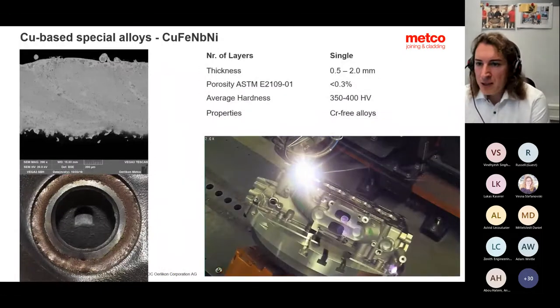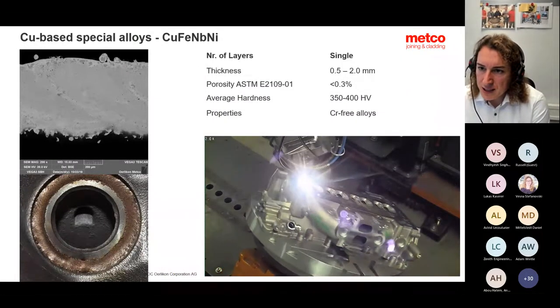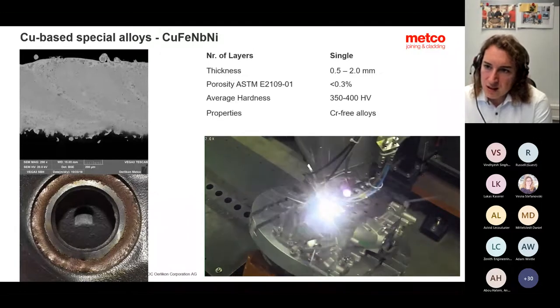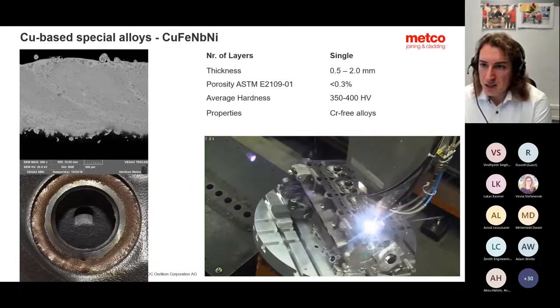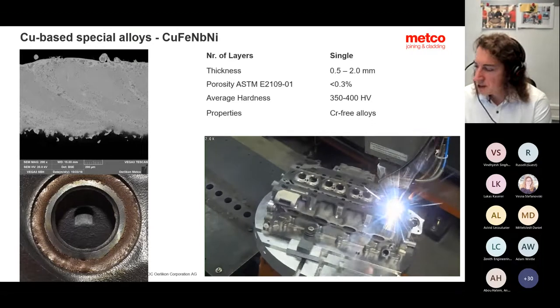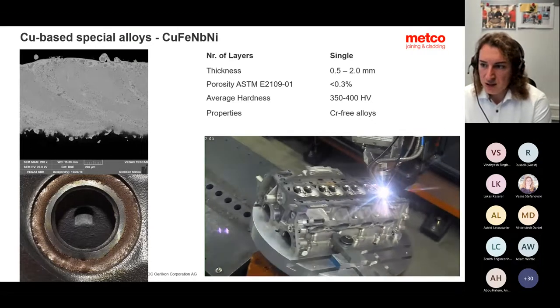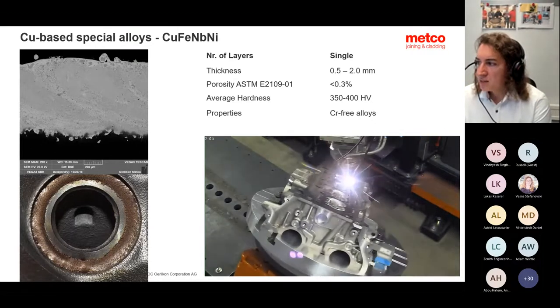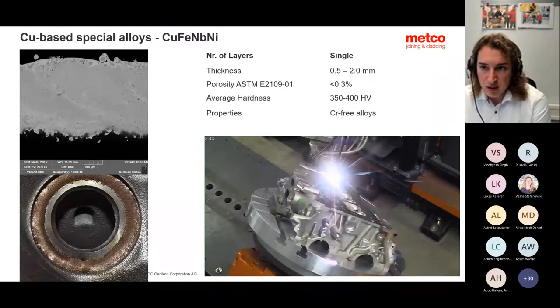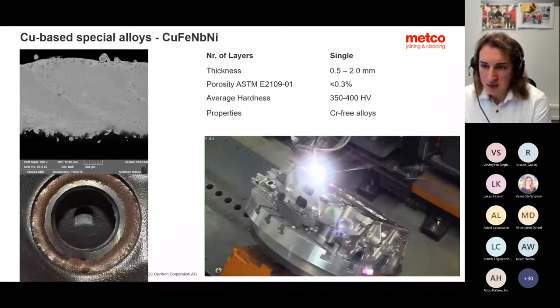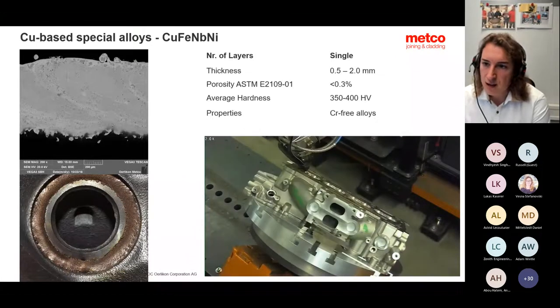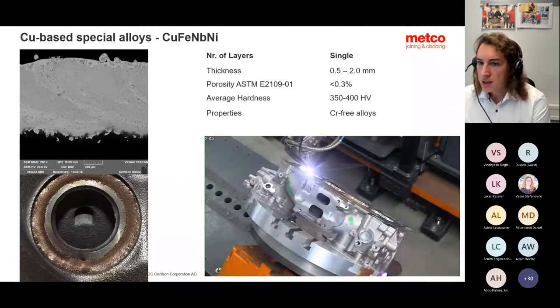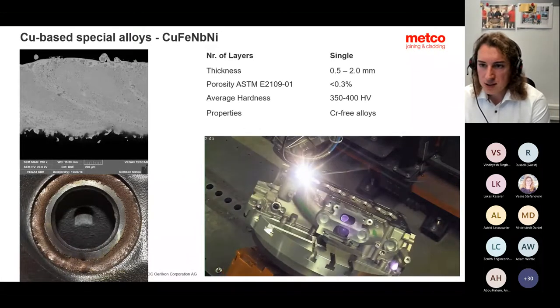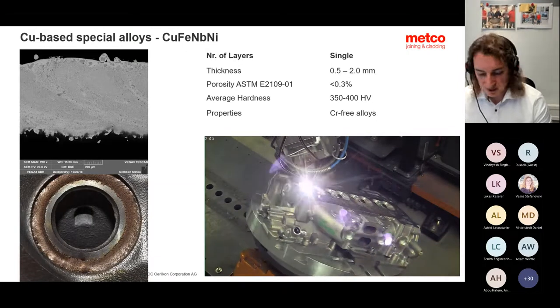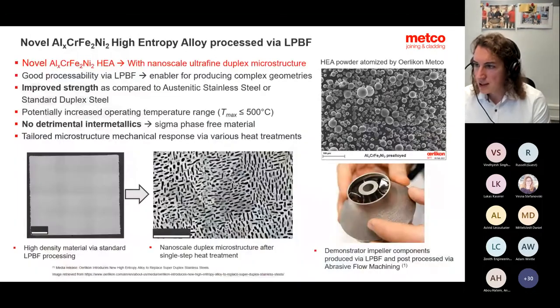Other examples where rapid alloy development has helped us to industrialize and qualify certain applications are related to valve seats, working with copper-based material on aluminium substrates, for example, producing chromium-free alloys, and having microstructure features without cracking or intermetallic formations to a certain extent. And this is also one of the examples where rapid alloy development can be used.